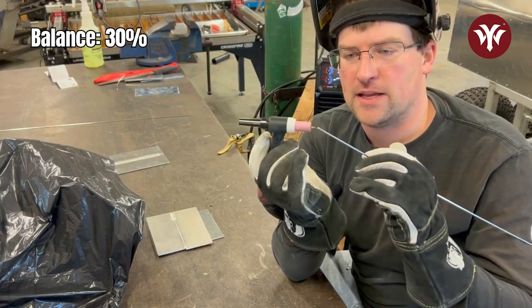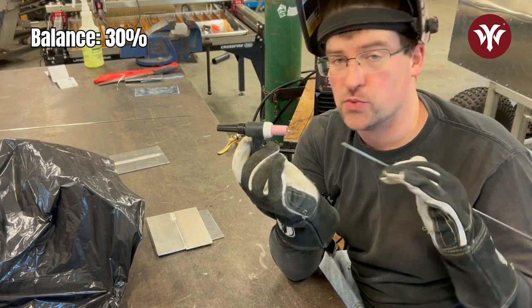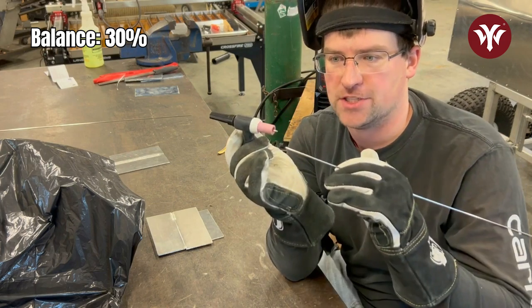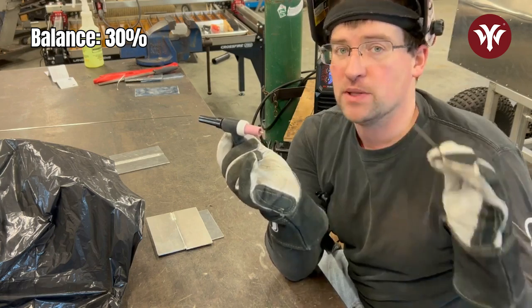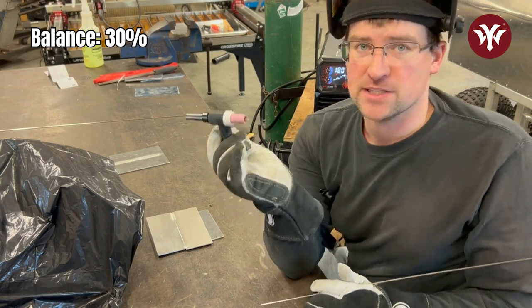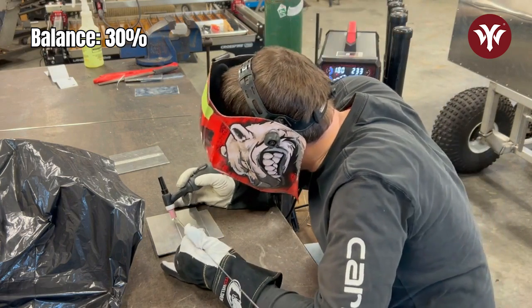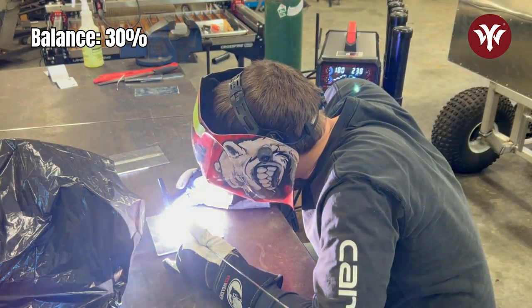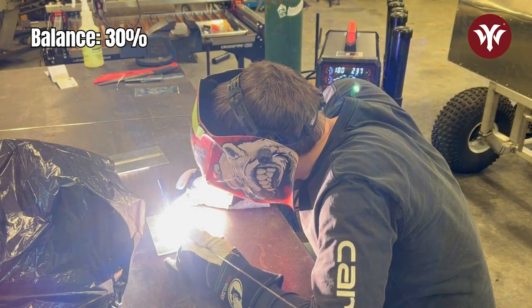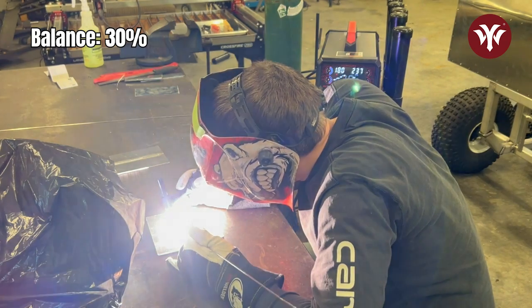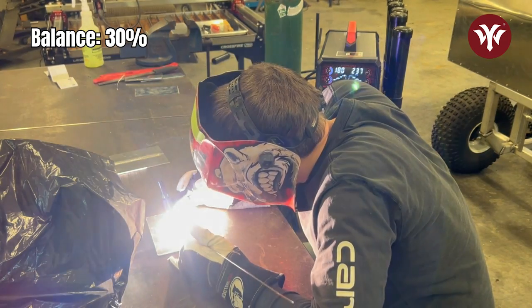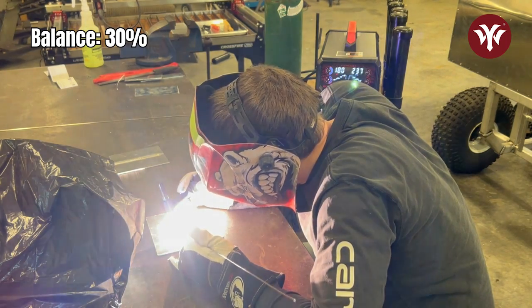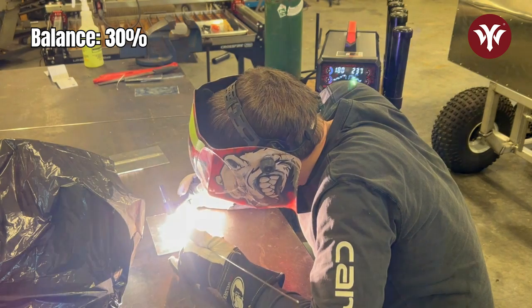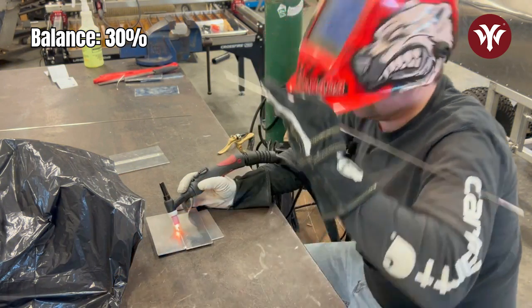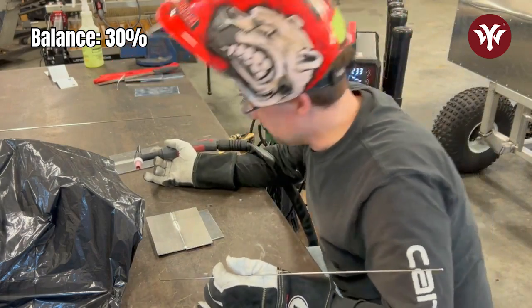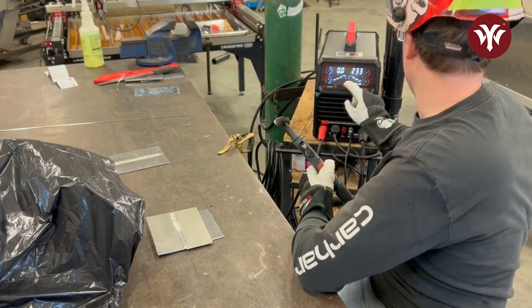The other thing I'm noticing is that tungsten now has no discoloration on it. So because we're using a really low balance and putting a lot of heat into the workpiece and not the tungsten, our post-gas flow is probably more than we need now, but it's keeping our tungsten from getting contaminated. All right, let's start a new bead and try this out. All right, so right away I can tell that bead is shinier. There is a lot less contaminant floating on the top. Significant difference.